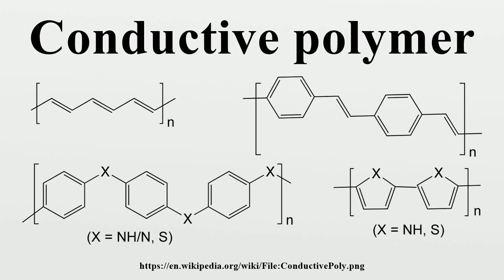Although typically, doping conductive polymers involves oxidizing or reducing the material, conductive organic polymers associated with a protic solvent may also be self-doped. Undoped conjugated polymers act as semiconductors or insulators. In such compounds, the energy gap can be greater than 2 electron volts, which is too great for thermally activated conduction. Therefore, undoped conjugated polymers, such as polythiophenes and polyacetylenes, only have a low electrical conductivity of around 10⁻¹⁰ to 10⁻⁸ S/cm. Even at a very low level of doping, electrical conductivity increases several orders of magnitude